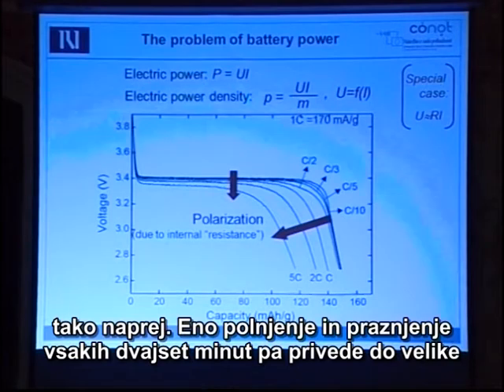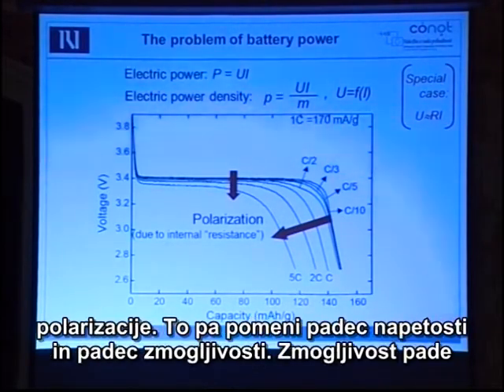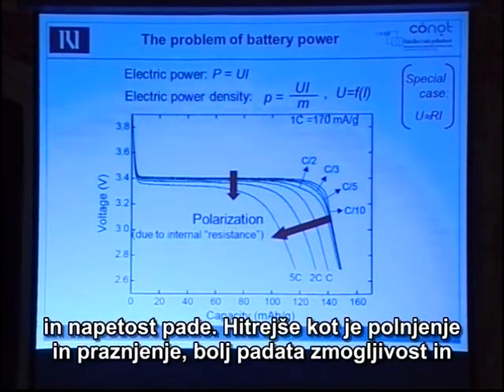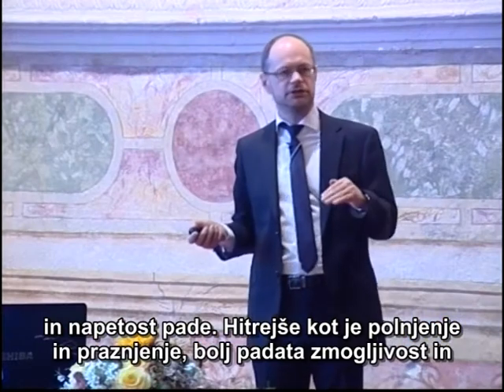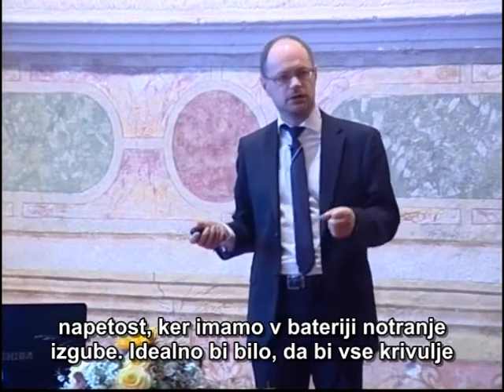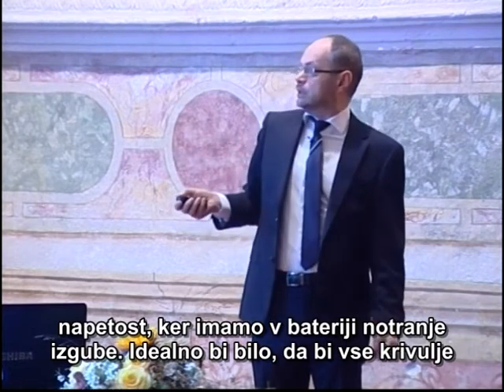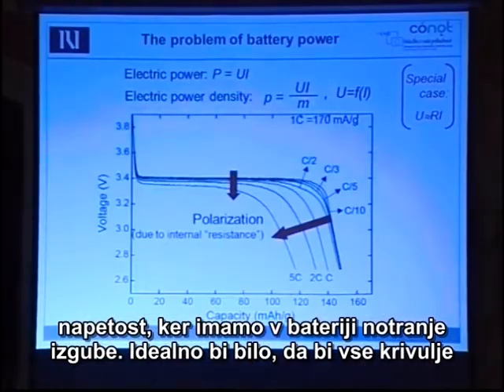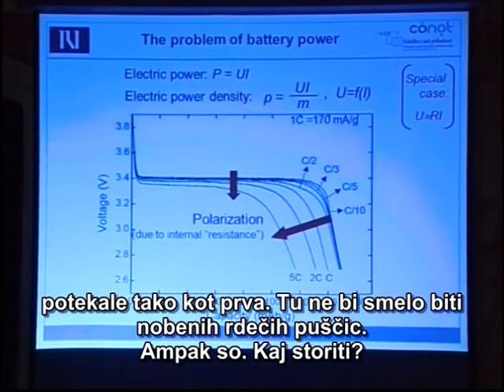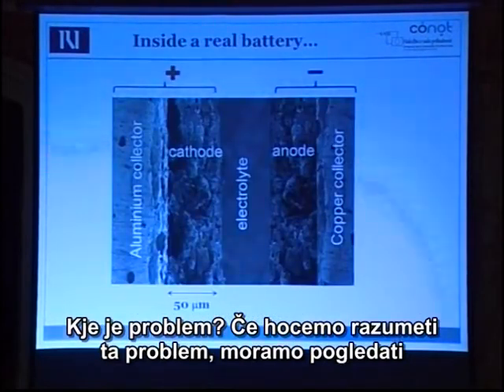So in 20 minutes, charge, discharge, you see a big polarization. This means a drop of your voltage here, and a drop of your capacity. Capacity drops, voltage drops. So the faster you charge, discharge, the more the voltage and the capacity drop, because you have internal losses in your battery. Ideally, all the curves should go according to the first one. So there should be no red arrows here, but there are. What to do? Where is the problem?